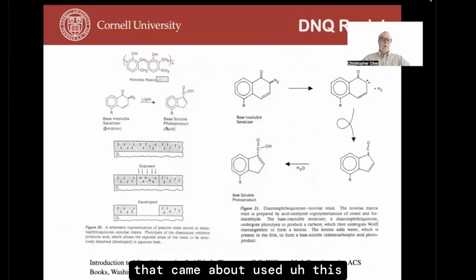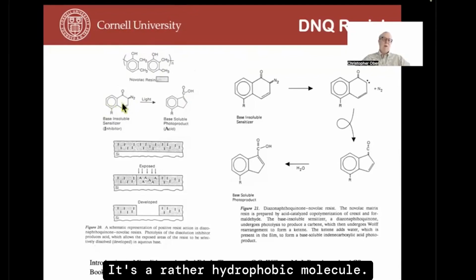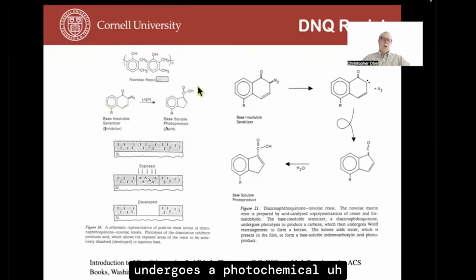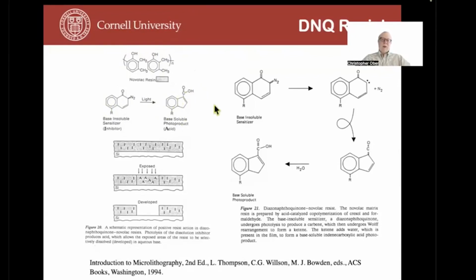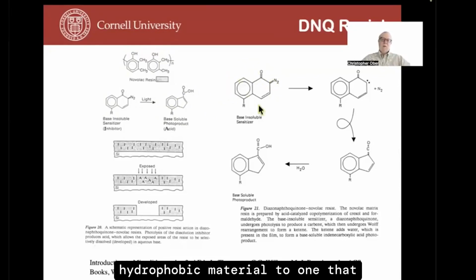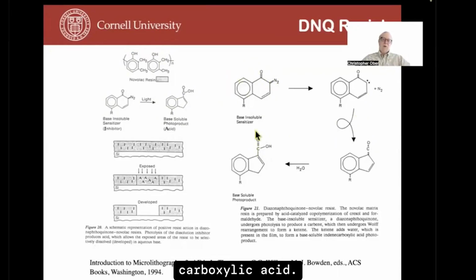one of the first new chemistries that came about used this interesting concept of a dissolution inhibitor. So it involved taking Novolac, which is one of the first synthetic polymers from the late 1800s, and blending it with diazonaphthoquinone. And what happens is the diazonaphthoquinone added to the Novolac makes it insoluble. It's a rather hydrophobic molecule. But on exposure to light, it undergoes a photochemical rearrangement, a Wolff rearrangement, as it's known. And it goes from being this hydrophobic material to one that after rearrangement has a carboxylic acid, and so it's easily soluble in aqueous base.